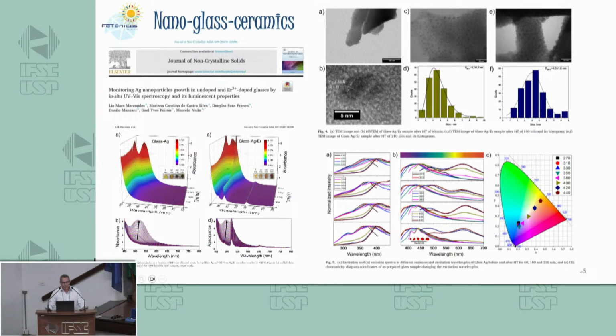So this is one possible way: to co-dope the glass with rare earths and metallic nanoparticles, and then try to transfer energy from the nanoparticles to the rare earths, and then increase the efficiency of emission. Okay? This is some basic study that we did in our lab. As Andrea showed us, we have the UV-Vis spectrophotometer, and we put a furnace inside the spectrophotometer where we can treat the glass and take the absorption spectra in situ during the treatment.